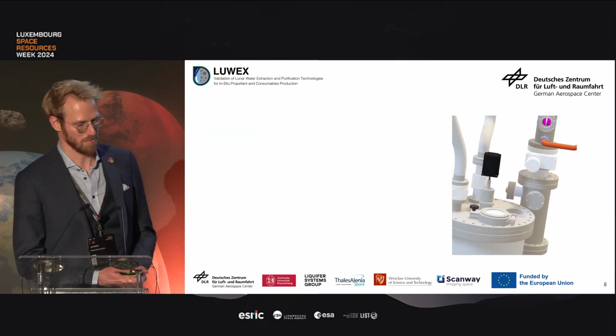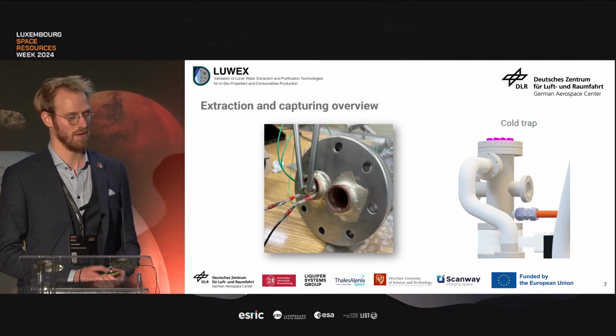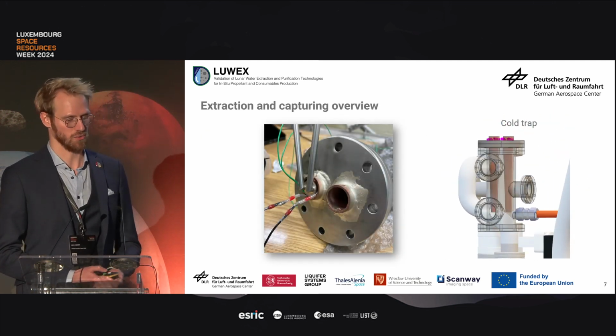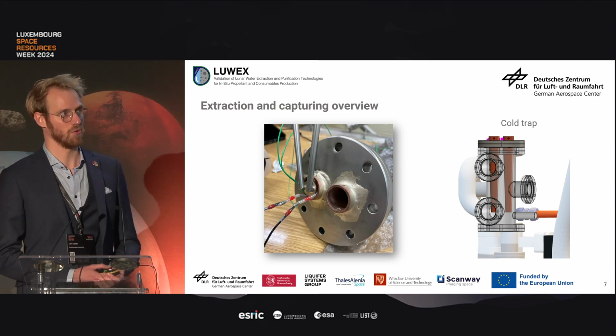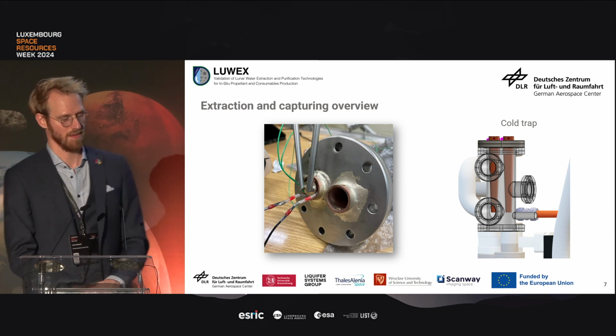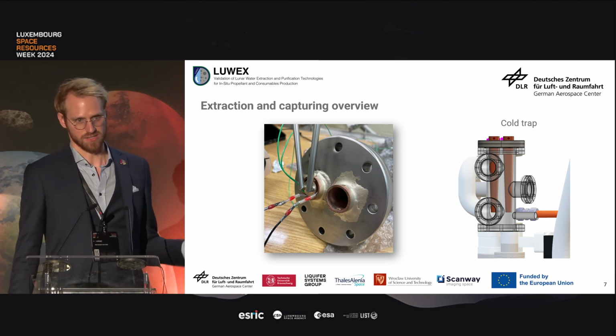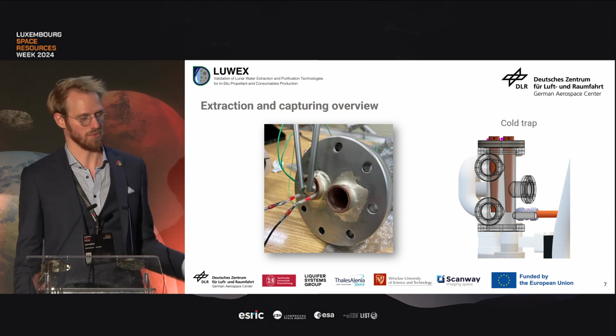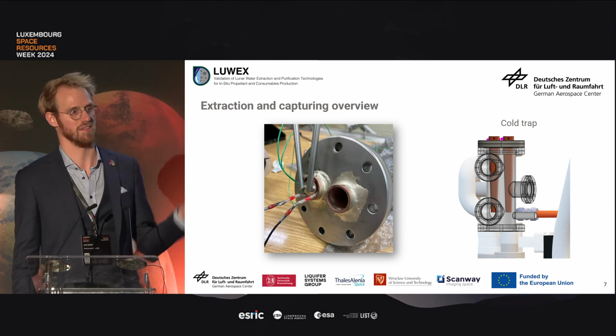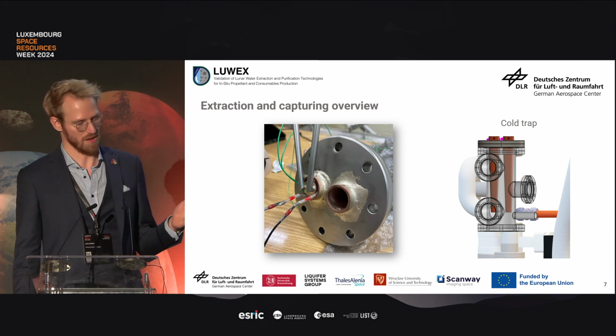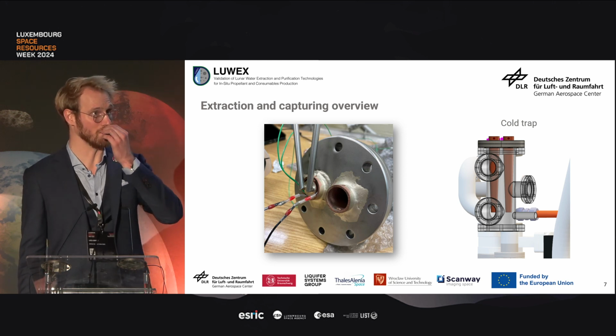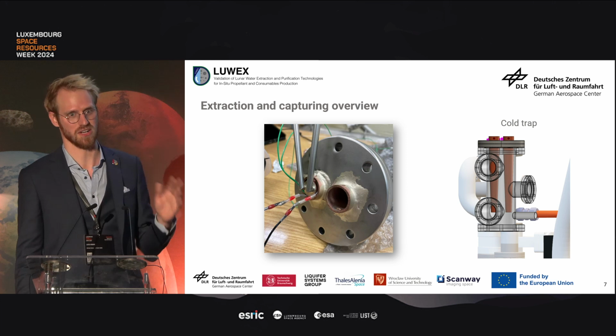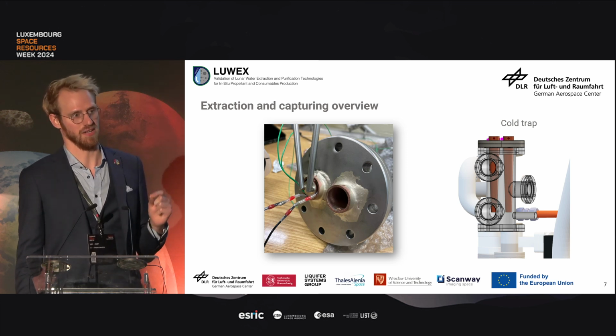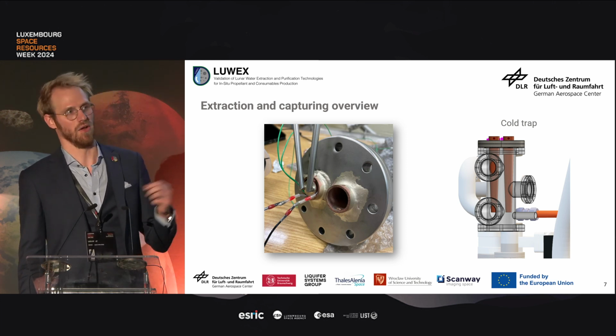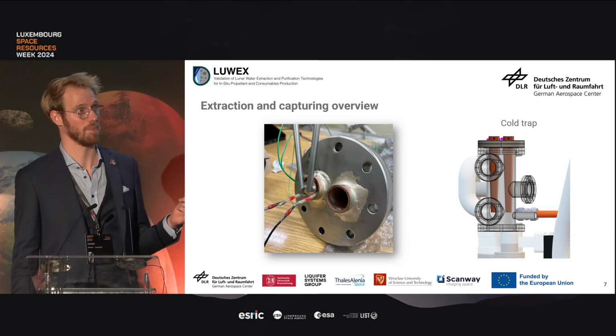So when the ice is sublimating, up next is the cold trap. In our cold trap, we have 2 cold fingers that we can both cool and heat, so we can accurately control the surface temperature. The idea is that all the ice that is sublimating from the regolith sample finds its way towards the cold trap, and it deposits again. And once it's there, because we control the temperature to roughly 190 Kelvin, we only capture the ice, or the water, and not the other volatiles like methanol, for example.